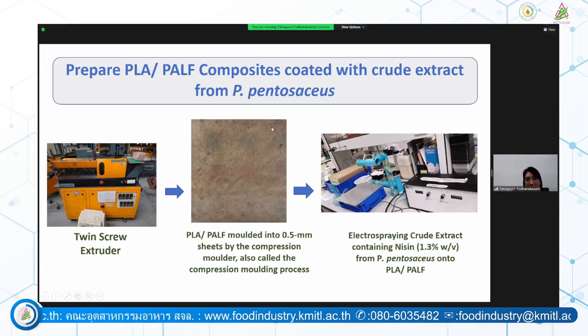After that, we cut it into small pieces in order to test whether the material, after being coated with the supernatant containing nisin from the Pediococcus, can inhibit the growth of our target foodborne pathogens. Okay, so how do we coat it? We take this sheet and cut it into coupons of about one by one in diameter, and then we place it into the electrospraying machine and spray with the needle. This uses high voltage, and we spray nanoparticles with the supernatant that we gain from the Pediococcus, which contains about 1.3% nisin. This solution is already neutralized, so we want to make sure that the effect on the pathogen isn't caused by the acid produced by the lactic acid bacteria, but by the nisin itself.